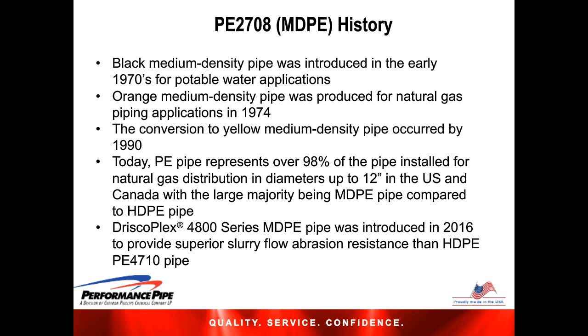Black medium-density pipe was first introduced in the early 1970s for potable water applications. Then, orange medium-density pipe was produced for natural gas piping beginning in 1974. By 1990, the orange medium-density gas distribution pipe was converted to yellow medium-density pipe. Yellow became recognized as the standard color for gas distribution piping in North America. Today, PE pipe represents over 98% of the pipe installed for natural gas distribution in diameters up to 12-inch in the U.S. and Canada, with the large majority being medium-density polyethylene pipe compared to high-density.